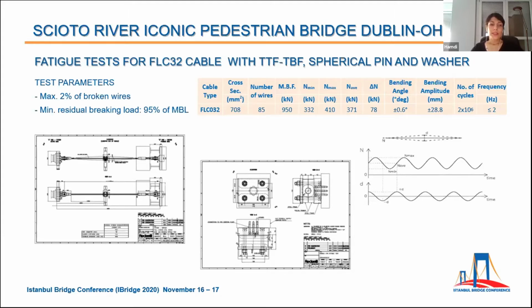And after the end of fatigue test on the cable, a breaking test has been carried out. The breaking test of this fatigued cable should be at least 95% of the original breaking force. It means if the cable breaks before 95% of minimum breaking load, the test is failed. And in our case, luckily, the results were satisfactory.